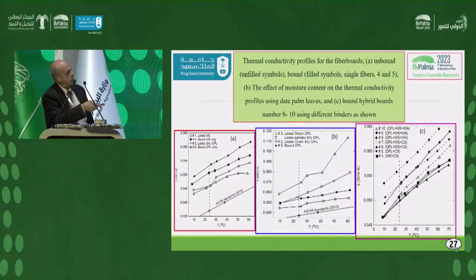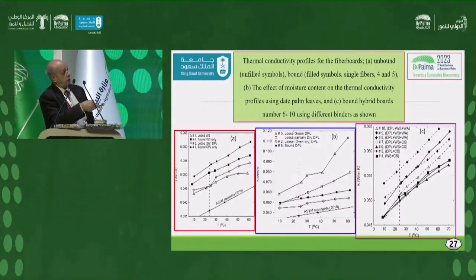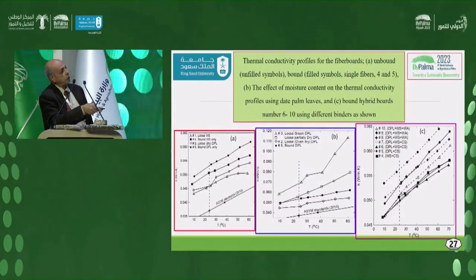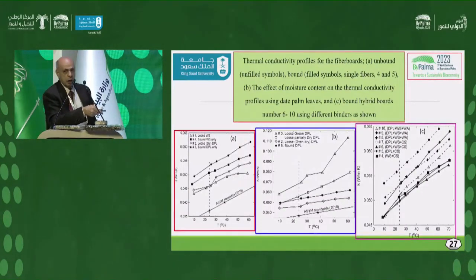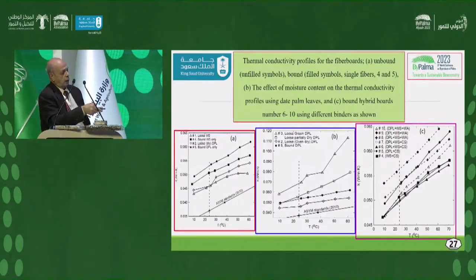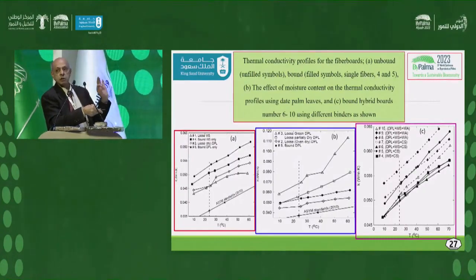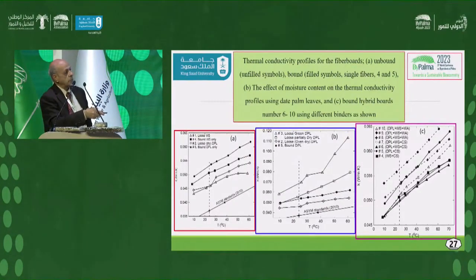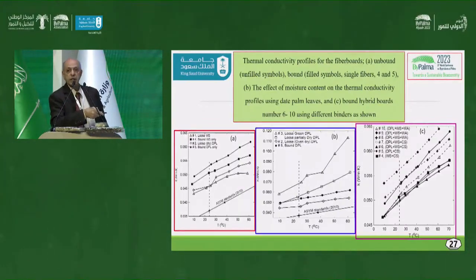As you see here, the loose fiber, of course, has a lower thermal conductivity, and when you add the binder, it increased. And this shows the effect of moisture on the palm tree leaves. If the palm tree is not dry enough, it means it has a little water, so it will give a high thermal conductivity, like this one. When we oven dried it, we get this one. So it's very good when it's dry. Okay, and these are the thermal conductivity for all the hybrid samples, and all of them below 0.065. So it's very good to be used as a thermal insulation.